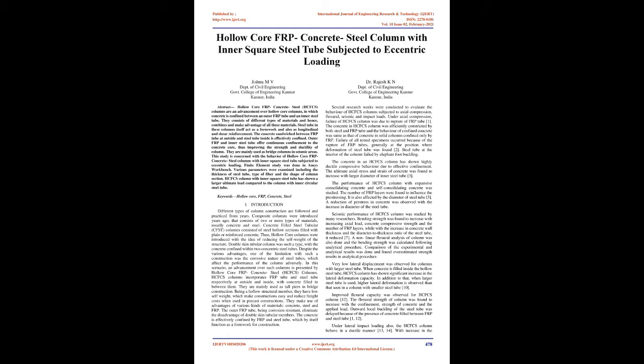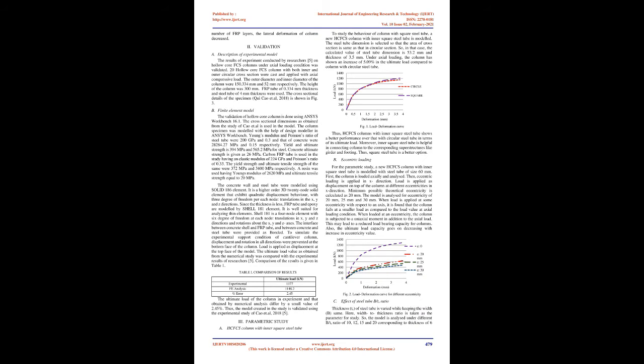Several research works were conducted to evaluate the behavior of HCFCS columns subjected to axial compression, flexural, seismic and impact loads. Under axial compression, failure of the HCFCS column was due to rupture of the FRP tube. The concrete in the HCFCS column was efficiently constrained by both steel and FRP tube, and the behavior of confined concrete was the same as that of concrete in solid columns confined only by FRP. Failure of all tested specimens occurred because of the rupture of FRP tubes, generally at the position where deformation of the steel tube was found too. The steel tube at the interior of the column failed by elephant foot buckling. The concrete in an HCFCS column has shown highly ductile compressive behavior due to effective confinement. The ultimate axial stress and strain of concrete were found to increase with larger diameter of the inner steel tube.